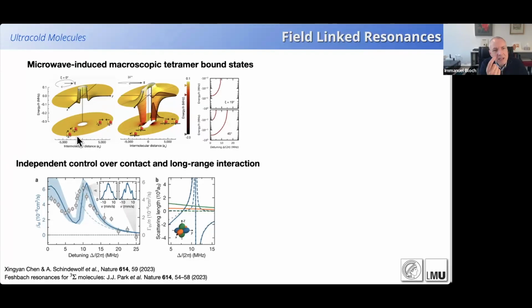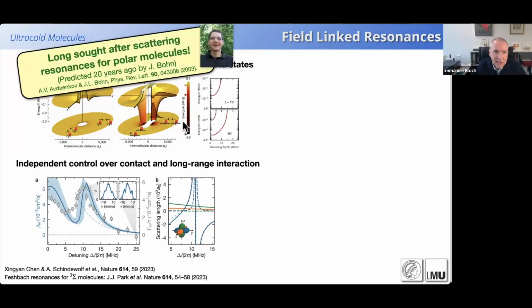And now by basically tuning the ellipticity of the microwave field, going from a circularly polarized microwave field to an elliptically polarized microwave field, we can really tune these molecular collision curves, these molecular potential curves, to a very high degree. And we can actually tune, for example, the depth of this molecular potential curve and thereby introduce bound states into this molecular potential. These bound states that are now introduced into these colliding molecular potential curves can then give rise again to scattering resonances. And these are so-called field-linked resonances.